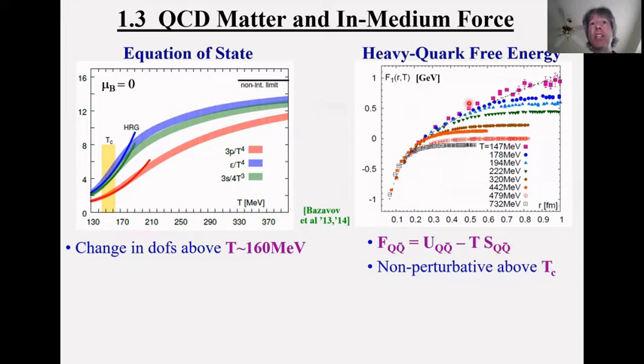Now, lattice QCD can also measure very well the partition function of a heavy quark pair embedded into the medium. And this is shown on this plot. Now, at zero temperature, this free energy actually just becomes the potential that I discussed earlier, shown by the dashed line. But at finite temperature, we see that indeed there is an expected screening of this free energy or potential. It's not really a potential, as we'll see later. But even so, in a way, the screening is remarkably weak, if you wish, because even at temperatures that are already well above the transition temperature, say of 160 MeV, the free energy still shows rather prominent non-perturbative effects in terms of this linear part of the potential still being present.